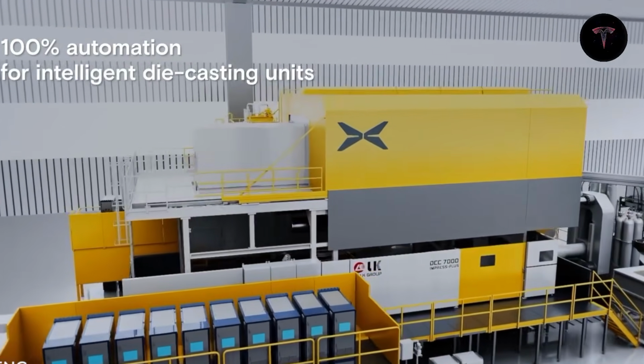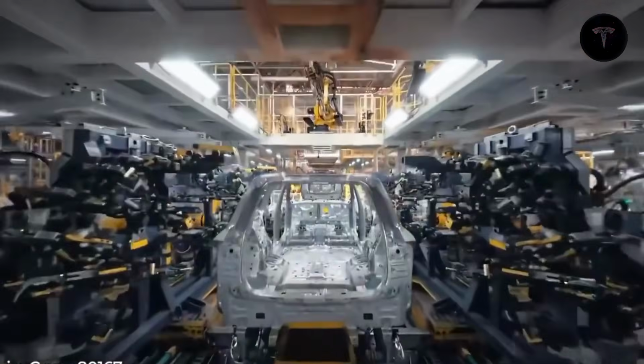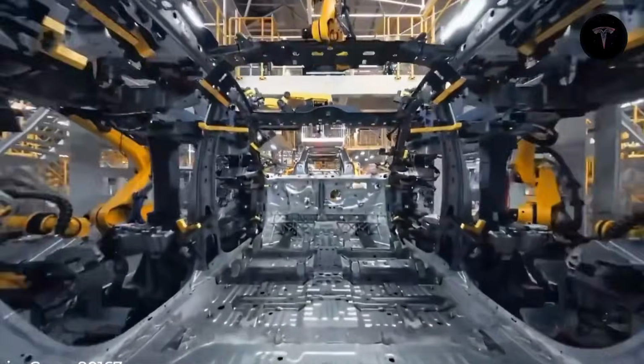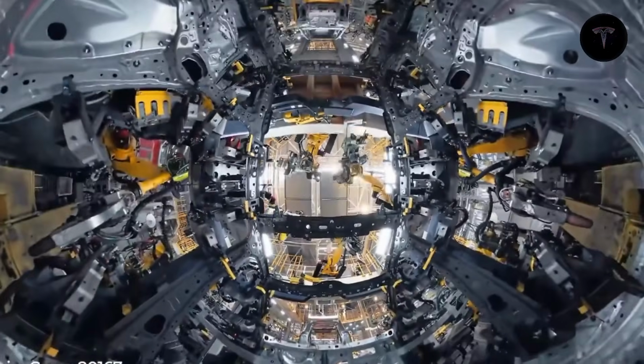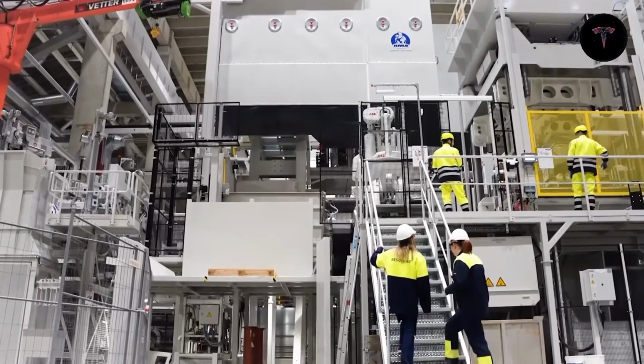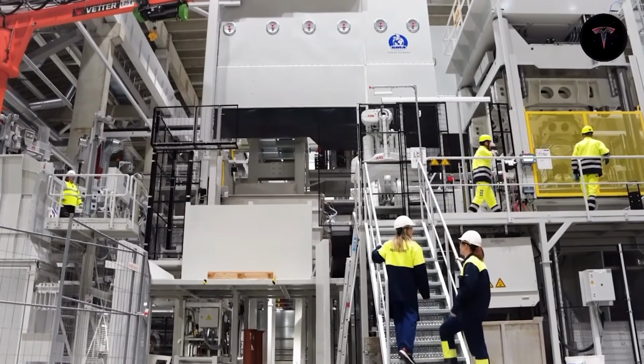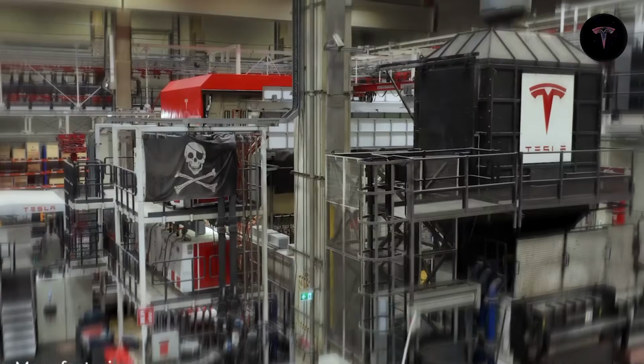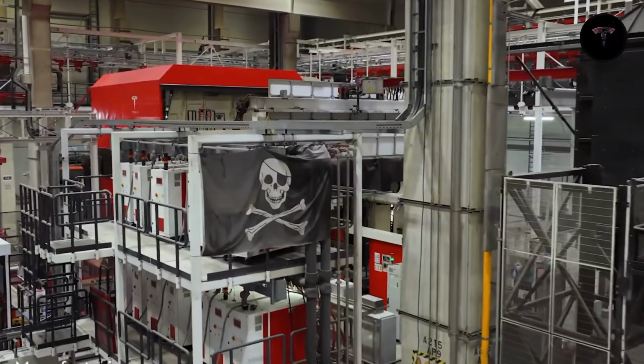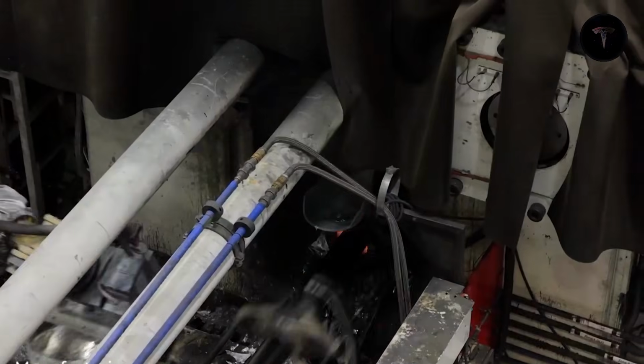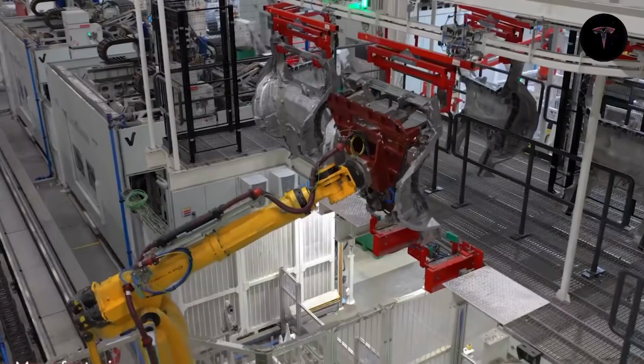A high-speed piston, itself lubricated with around 8 milliliters of oil per shot, then drives the molten aluminum into the mold cavity under the full clamping force of the press. The injection speed and pressure must be controlled precisely. Too fast traps air, too slow allows the aluminum to begin solidifying before the mold is completely filled.